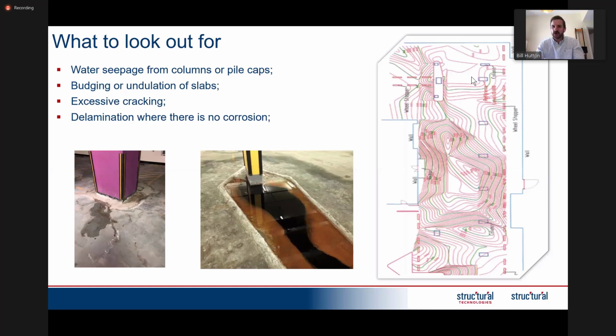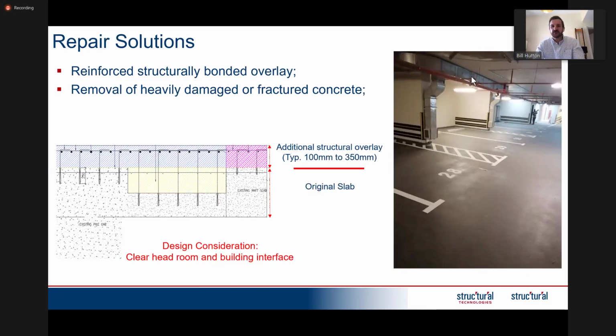In terms of the solution, generally it includes installation of a reinforced structurally bonded overlay and removal of any heavily damaged or fractured concrete. This is a simple diagram here. You can see that we're actually increasing the thickness of the slab. Typically you would install a structurally bonded overlay of between 100 to 350 millimeters on top of the existing slab. One of the biggest challenges with this type of repair is consideration of the headroom. Often there are MEPs, ventilation systems and firefighting systems installed on the soffits, so you need to make sure that you still adhere to the municipality requirements in terms of headroom.